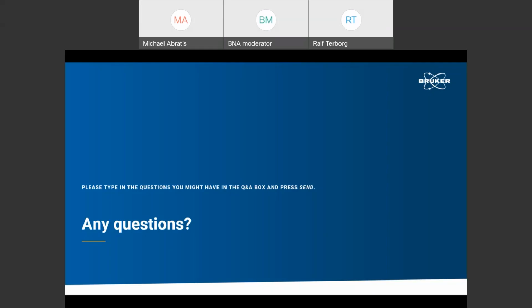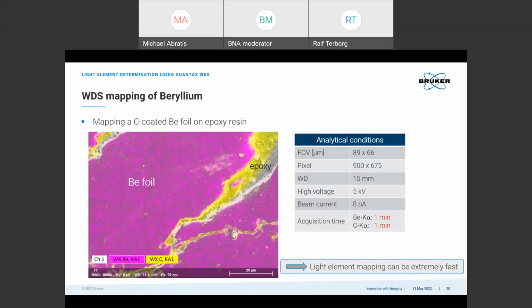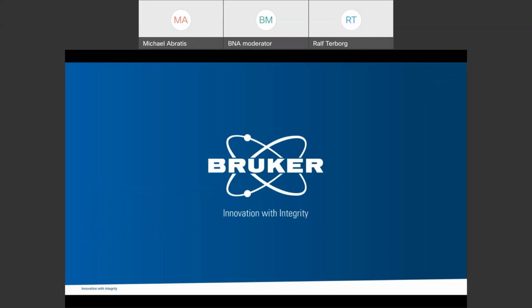Now we will proceed with application examples for the light elements. We will start with beryllium, the element with atomic number 4. This slide shows an element distribution map of a carbon-coated beryllium foil on epoxy resin. Mapping of the sample could be done very fast with an acquisition time of only 1 minute for each element. Remember that WDS is wavelength selective, so one element is mapped after the other, first beryllium, then carbon. For each element, the suitable multilayer mirror and the respective theta angle were automatically set to determine beryllium K alpha and carbon K alpha.